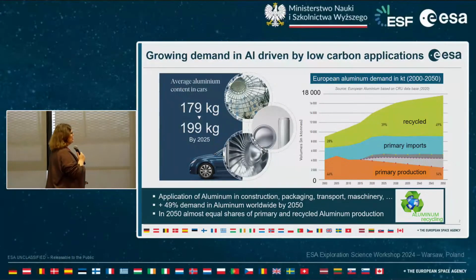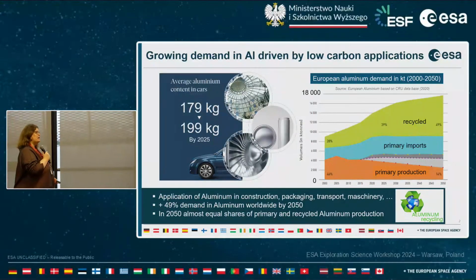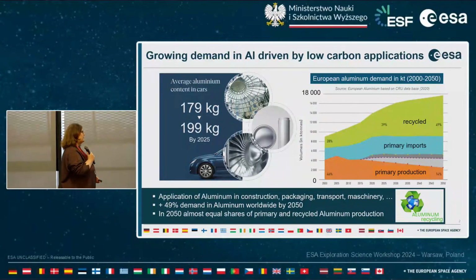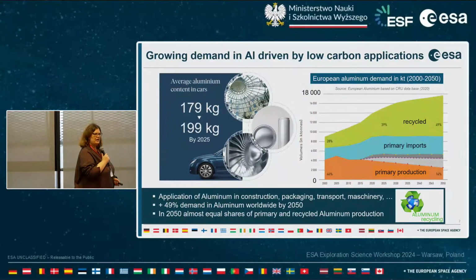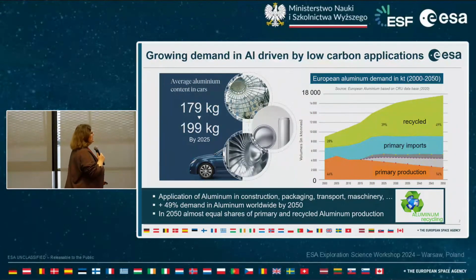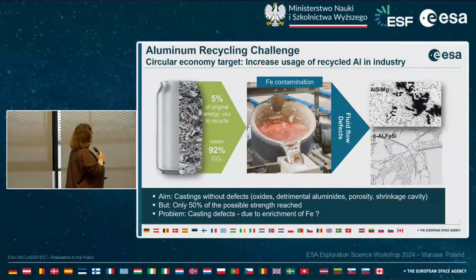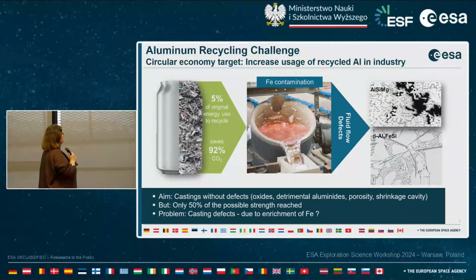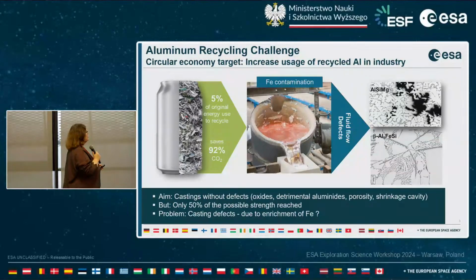And this strong demand for aluminum can only be met by almost equal shares of primary and recycled aluminum production. And for Europe, this means that increasing the production of recycled aluminum, of course, will decrease on the other side the dependency on the import of primary aluminum from third countries with a higher carbon footprint, and will also decrease the CO2 emissions, because for the production of secondary aluminum made from scrap, you need only 5% of the energy compared to the energy you need for primary aluminum production.